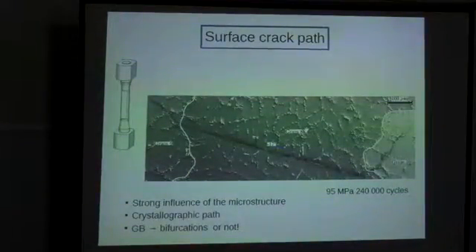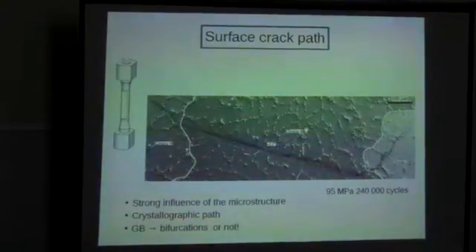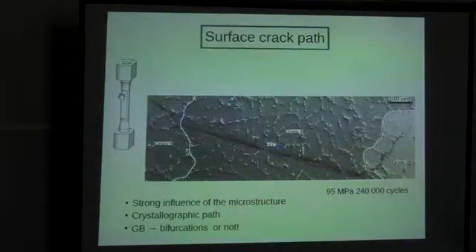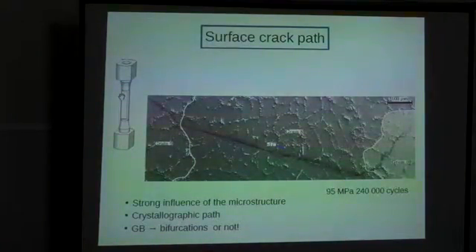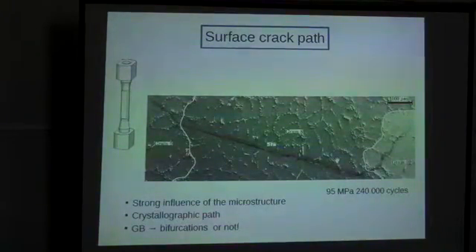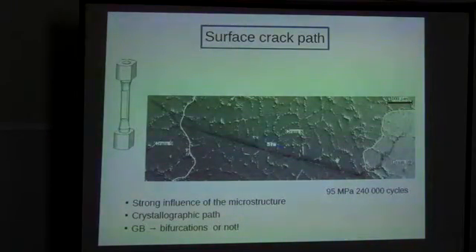What we know about the cracks in 2D is already quite a lot. By making a flat surface on the side of the specimen, you can observe the cracks once they initiate and as they propagate at the surface. What you typically see are some very long, trans-granular cracks which look very crystallographic — they cross a whole grain. Most of them are nearly perpendicular to the sample axis, but you also see some cracks which are parallel to the sample axis.